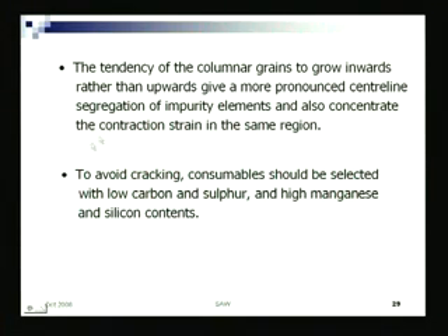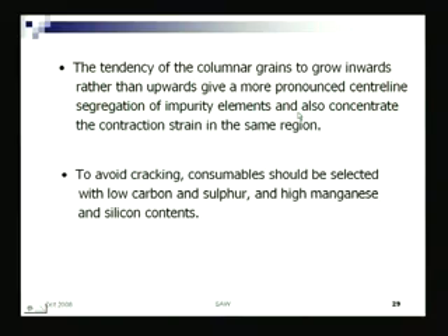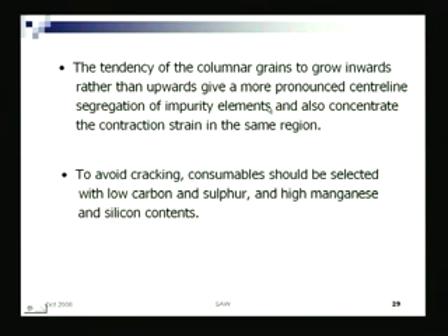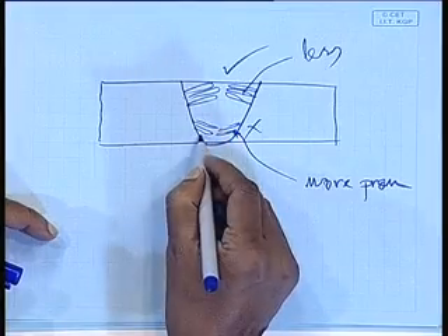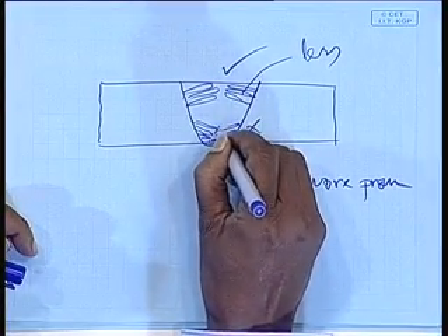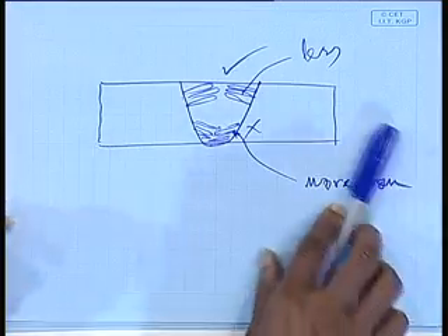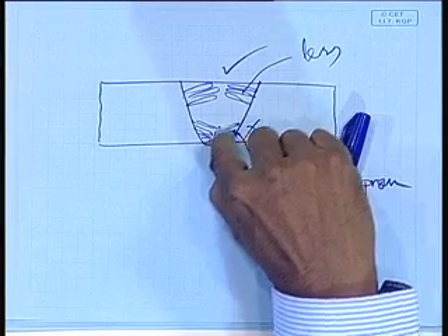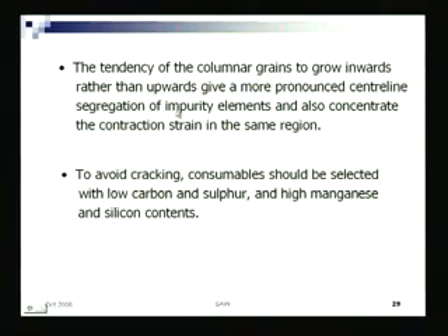So the tendency of the columnar grains to grow inwards rather than upwards gives a more pronounced central line segregation of impurity elements. These are some metallurgical aspects of how it happens, but it is nice to know what basically happens, and it also concentrates the contraction strain in that region. Because in this form, all the impurity elements get concentrated in that central region. Impurity elements means phosphorus, sulfur - those are the impurity elements. So if they are in higher percentage, they will get segregated and concentrated in the middle portion. This segregation of impurity will take place, along with contraction strain in the same region.